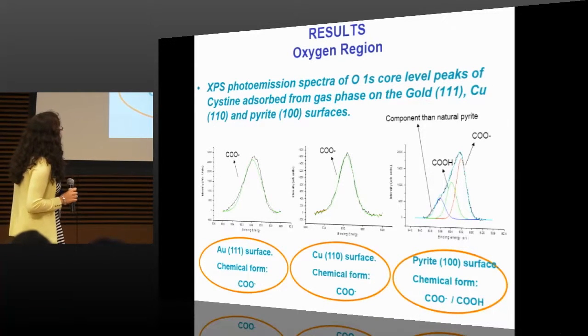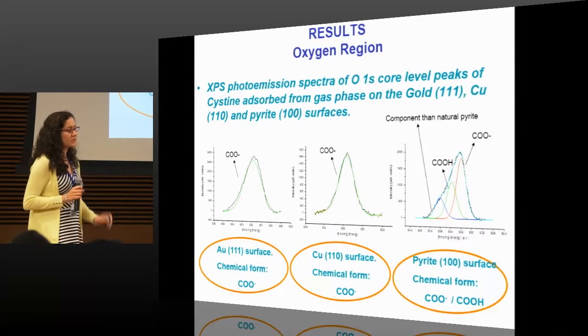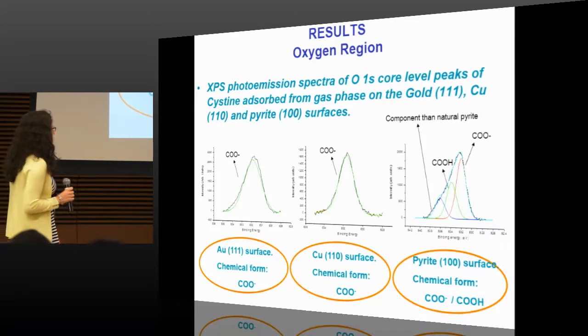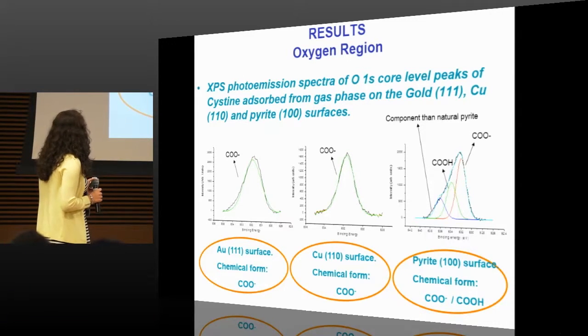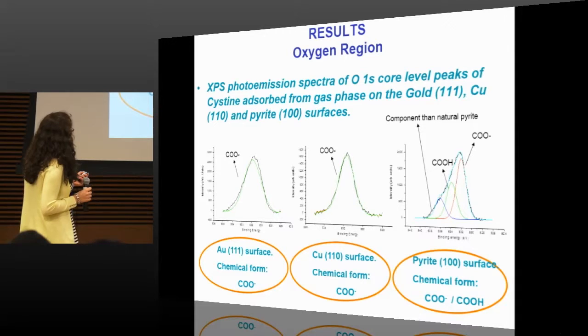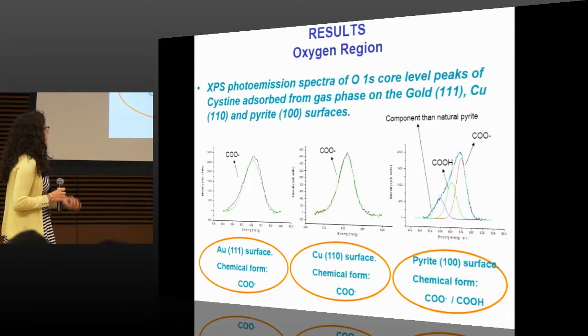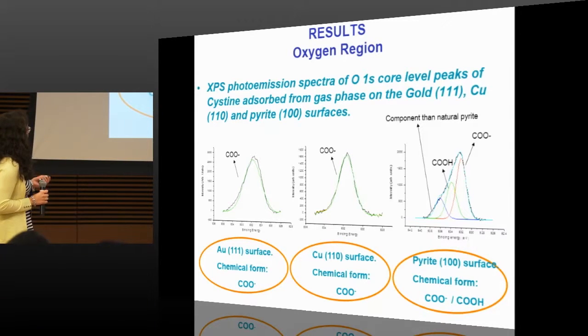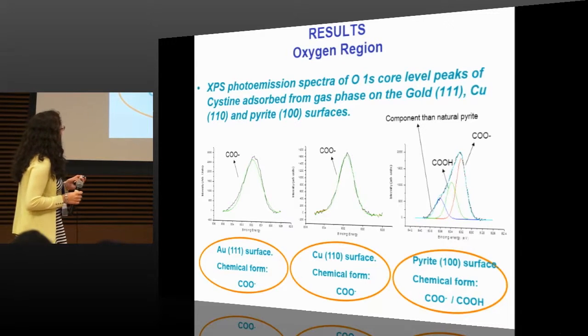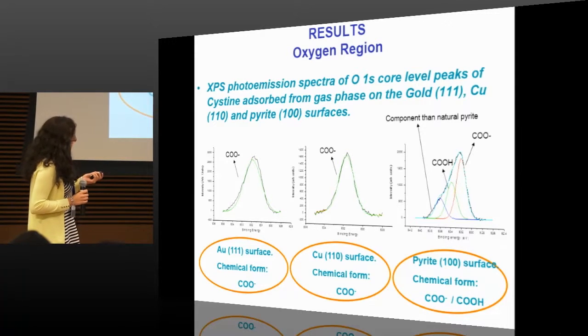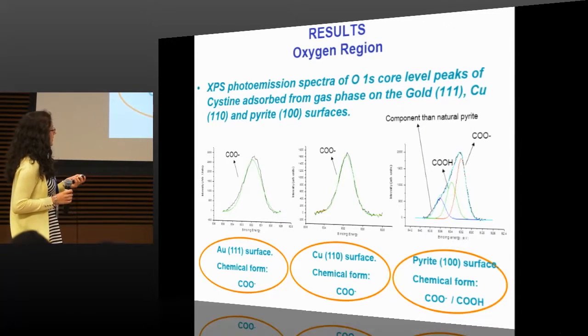In the oxygen region, we can observe some difference between the metals and the mineral surfaces. On the gold surface and copper surface, we can observe only one component. This component is the carboxylate group. The acid group is deprotonated on copper and gold. And on pyrite, we can observe two components, the carboxylate group and the acid group. And the other component is a component of natural pyrite, but is not oxygen.